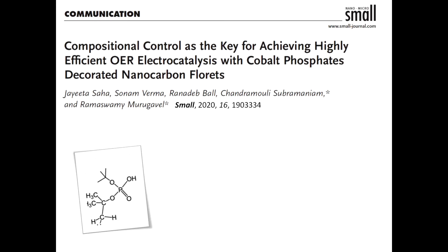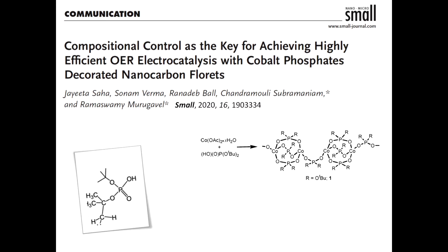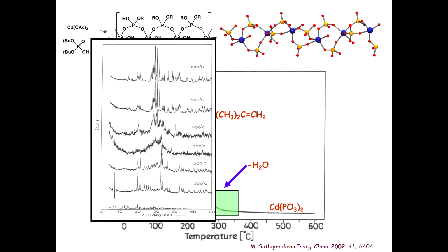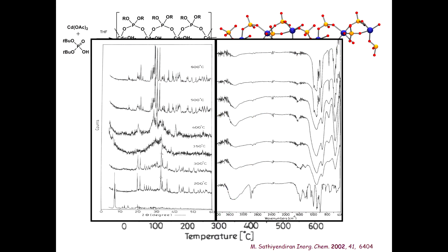So what we did in 2002, we took it up about two decades later. The only thing is we changed the metal from cadmium to cobalt, because by then I think Nocera had published his famous papers on cobalt phosphates, which would split water and produce hydrogen and oxygen. So we knew it was only a matter of time before we put this molecule into some use. It's a very simple reaction. The molecule is pretty much similar to what I showed in the previous slide, only the cadmium has been replaced by cobalt.